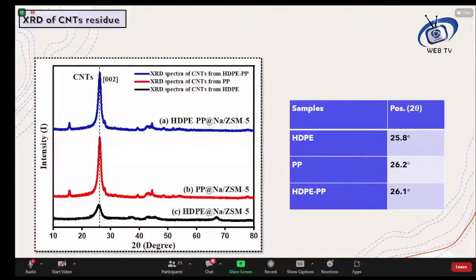So thereafter, the solid residue, which we assume is carbon nanotubes, we performed the XRD analysis of the residue, and we observed the peaks at 2 theta of 25.8 degrees, 26.2 degrees and 26.1 degrees. And the corresponding plane was 002, which shows that these were multi-walled carbon nanotubes. Some other peaks in the XRD analysis were also observed, which may be due to amorphous carbon, or due to the catalyst or the heat susceptor itself.